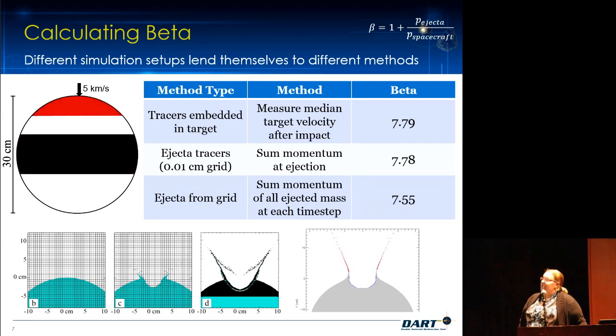We also put a tracer in the top to measure the ejecta momentum, and if you sum all the momentum there, you get almost exactly the same. And then we put a tracer in every single grid cell of the model and measured the ejecta moving through and summed up all of the momentum there. And we get within about 10% again of the momentum. So we're pretty confident that amongst the codes we'll be able to calculate beta in a variety of different ways that's well suited for each code, and it'll give us the same sort of answer.